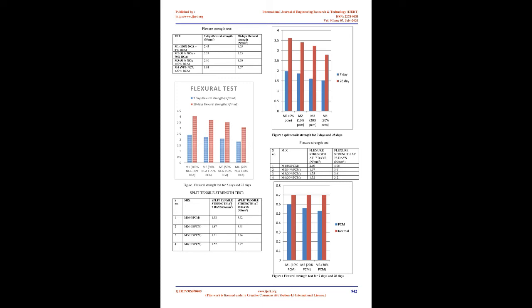Kaur et al., 2016, studied effects of using recycled concrete aggregates on the shrinkage of high-performance concrete. They reported that the plastic and drying shrinkage became higher as the quality of RCA decreases. Laneri et al., 2016, studied the influence of recycled coarse aggregates on normal and high-performance concrete subjected to elevated temperatures of 750 degrees C and reported that the residual performances for the recycled concretes were generally similar to but slightly worse than those observed for the reference concretes. Also, the presence of non-cementitious impurities accelerates the damage of concretes with temperature.